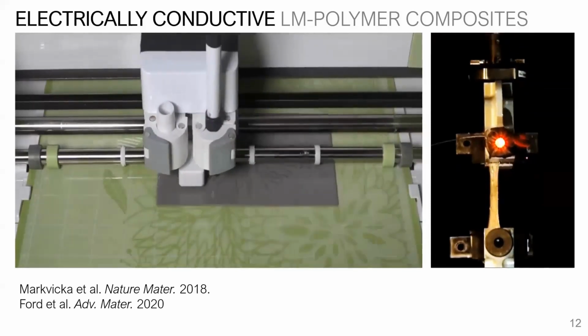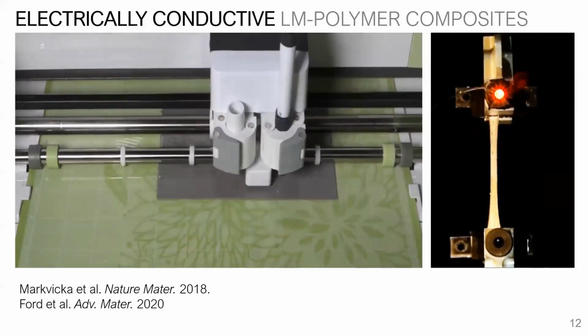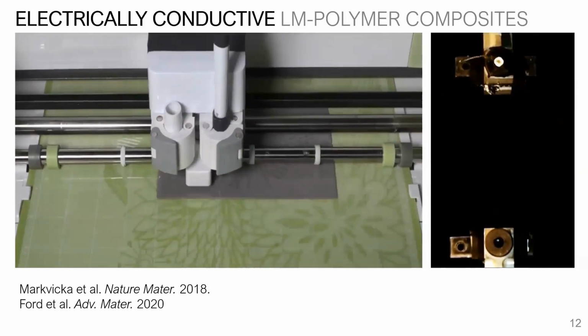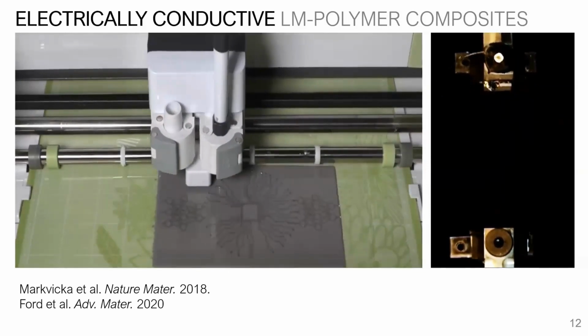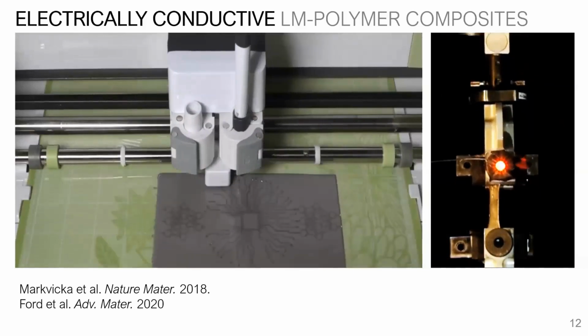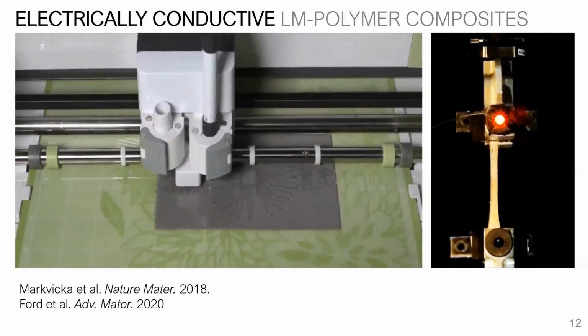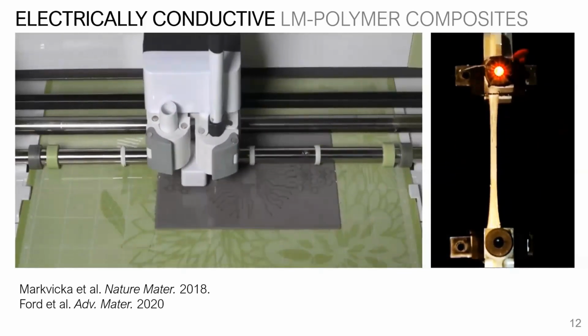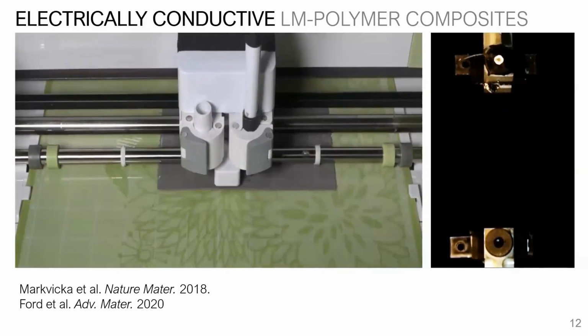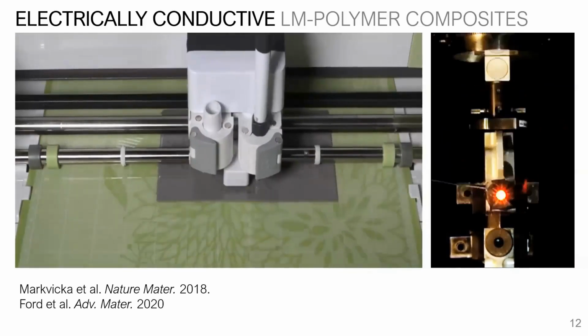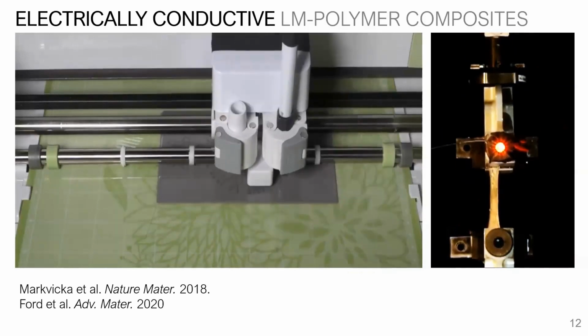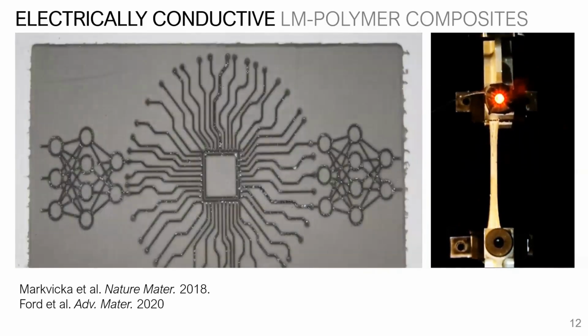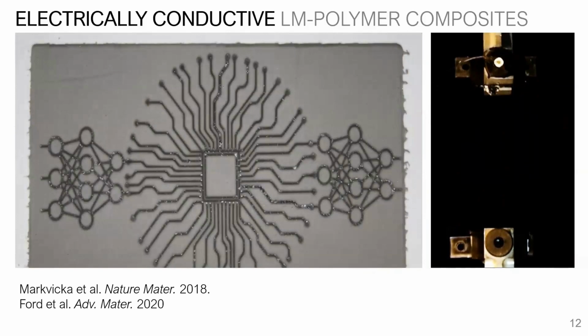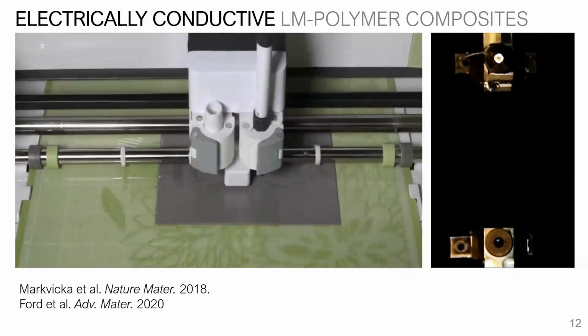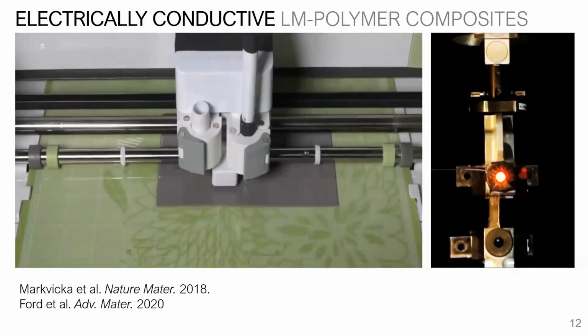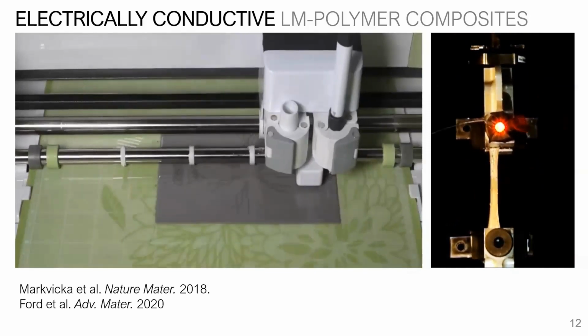But when you do get a percolating network of these droplets, you get something that's quite conductive and also quite stretchable. What's not captured in this video here, I'll run again, is that one nice feature of the microstructure of these LMEE composites is that their electric resistance is actually quite stable, even under really extreme strains. You can stretch these to 500% strain, 600% strain, right? So, 6-7 times their natural length, and you see virtually no change in electrical resistance. You still are able to maintain, say, 1 ohm or half an ohm.